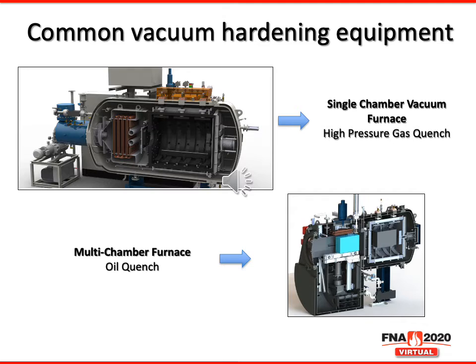But here, instead of the heating and quenching cycles happening in the same chamber, the batch actually processes through a heating and quenching chamber separately. This allows for the oil vapors that are produced during the quench to be managed without damaging the internal portions of the heating chamber itself. Both of these furnaces are capable, and we'll show in a moment a bit more how they're capable. So, what's the problem? Why is distortion an issue?